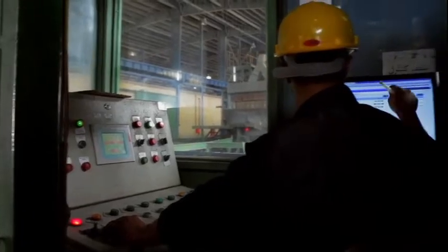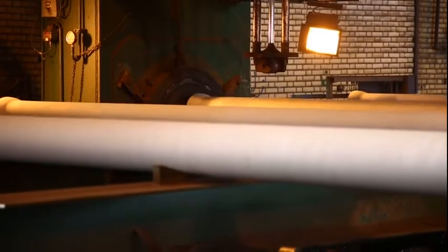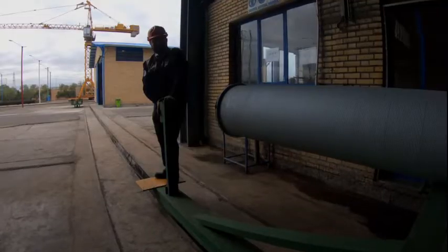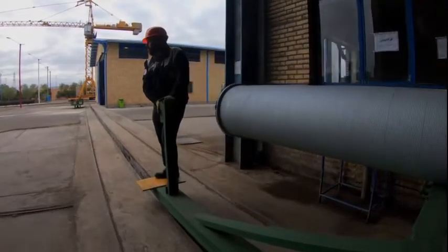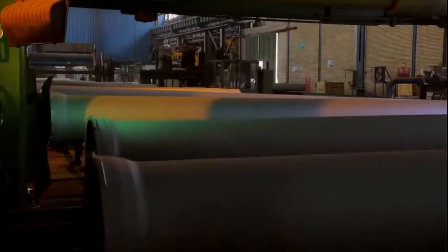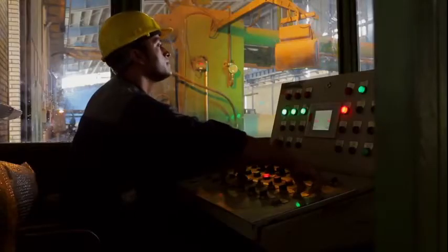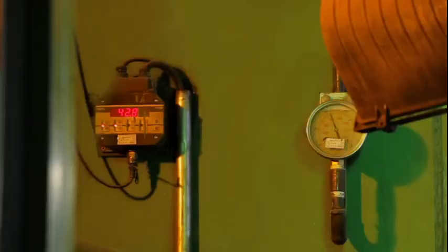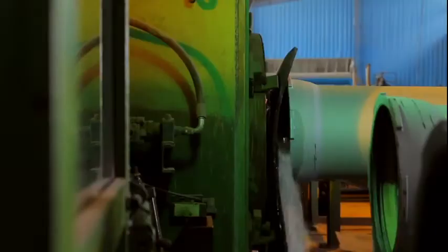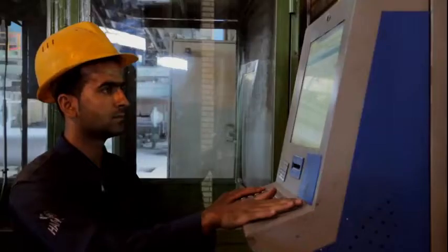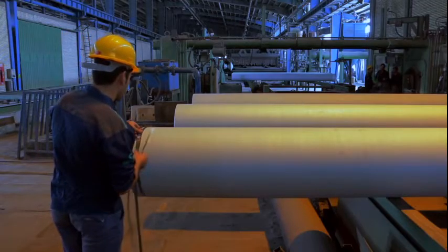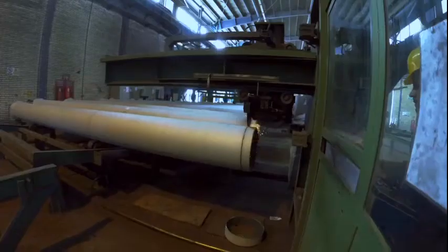After the galvanizing, pipes are forwarded to hydrotest station while lighting poles are conveyed to the paint workshop, since lighting poles do not need to hydrotest. Hydrotest is a non-destructive method to distinguish a leakage or crack in the pipes, which is done at different values up to 53 bar depending on the pipe class and standard requirement. Dimensional inspection and appearance control of products during various operations are performed according to the standard.